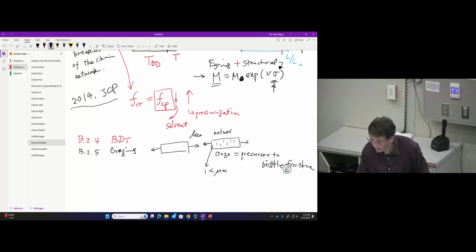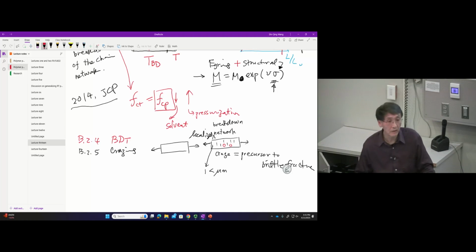So if you like, it's a localized breakdown of the network. Part of the reason I'm skipping this is because we're running out of time, but also this remains a poorly understood phenomenon. Crazing is where weakness occurs, so it has a little crack happening. And then you ask, why doesn't it craze here? Why doesn't it craze here? The only hand-waving explanation is that somehow this network is not uniform in terms of strength. Some parts are simply weaker than others.